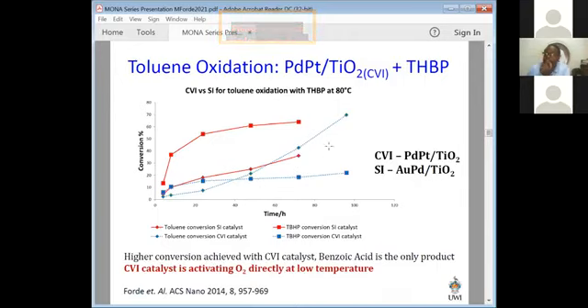So if you check the amount of oxygen in the product versus the oxygen that could have possibly come from the TBHP, you realize that oxygen is coming from somewhere else, and it turns out that it's coming from air. So this material activates molecular oxygen directly at quite low temperature. So we use this as the basis to continue some further reactions, some further investigations.